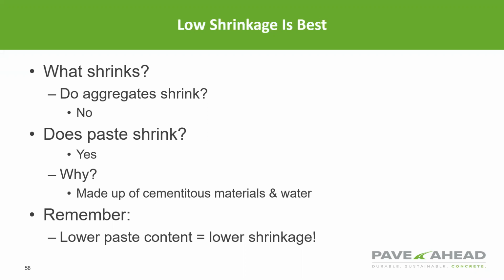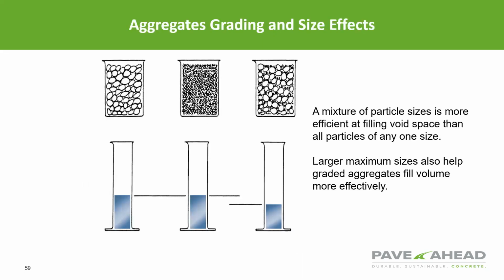The aggregates aren't going to shrink. It's the paste, so if you have lower paste content, aggregate grading matters. It shows how much paste is needed. With optimized gradations, there is less paste and water demand, while slump and workability stay the same as mixtures with single-sized aggregates. So what this shows you is if you have mostly the same size or a small same size, you're going to have more surface area, and paste is going to be required to coat it. If you have a well-graded mixture, there is less paste and less water, thereby less shrinkage in the pavement.